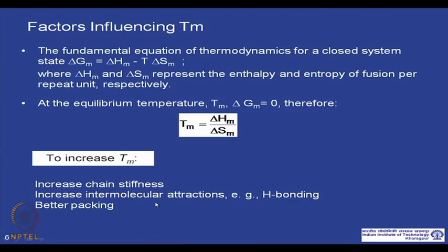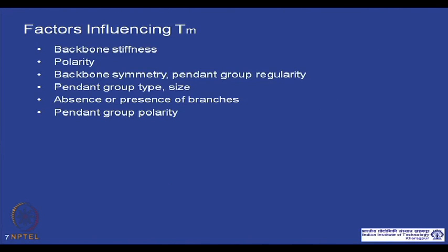Similarly, you can increase the intermolecular attraction, you can introduce specific bondings like hydrogen bonding that will increase the enthalpy, delta H of melting, and by that we can increase the melting point. And obviously, better packing always improves the melting point of the polymer.